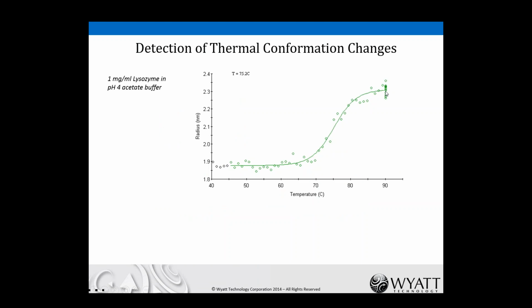And then the temperature is held here, 90 degrees. Now these data were not taken in the plate reader because it only goes up to 85. It was taken in our other dynamic light scattering instrument, the Nanostar. And when you hold it at 90 degrees, the size is not changing, and that means that it's basically not aggregating. So you could do a scan and hold. You could go up to a particular temperature, and you can hold at that temperature and assess the rate of aggregation. That's one of the possibilities with dynamic light scattering. And lysozyme here does not aggregate, we can see clearly, and we can actually ramp the temperature back down, and it would nicely refold.